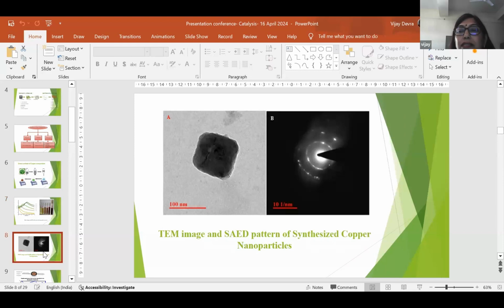The synthesized nanoparticles are also characterized by transmission electron microscope study and the selected area electron diffraction study. The TEM analysis results explain that the synthesized nanoparticles are cubical in shape, with an average particle size of 49 nanometers. And the selected area electron diffraction pattern indicates the synthesized nanoparticles are highly crystalline.